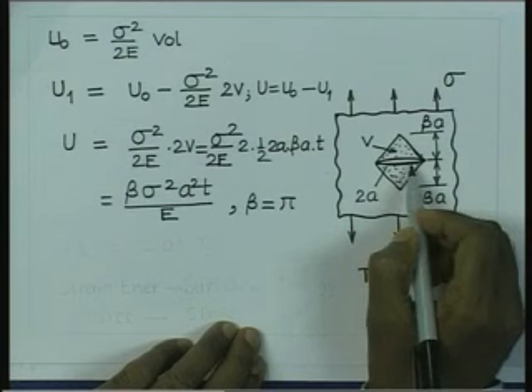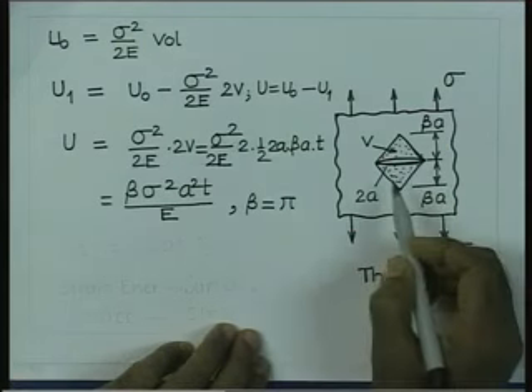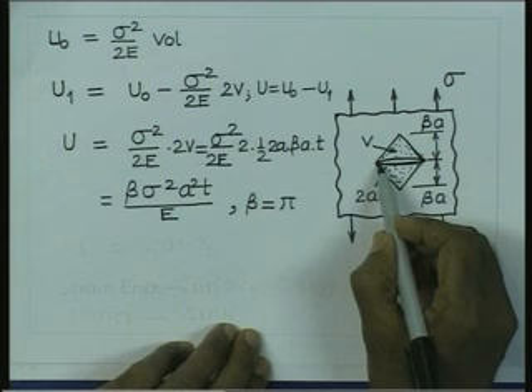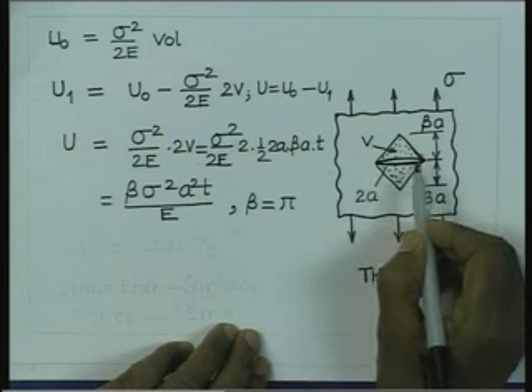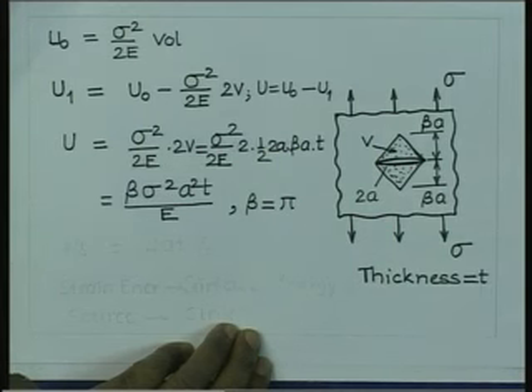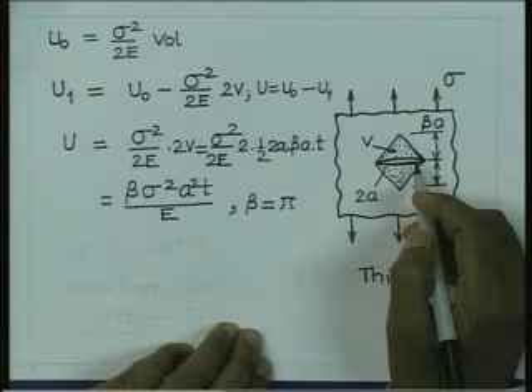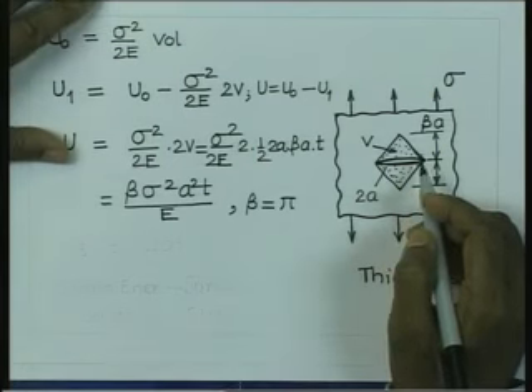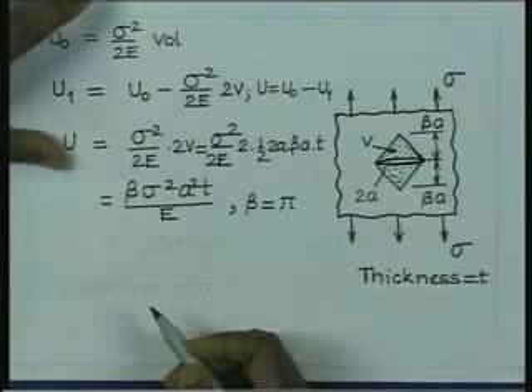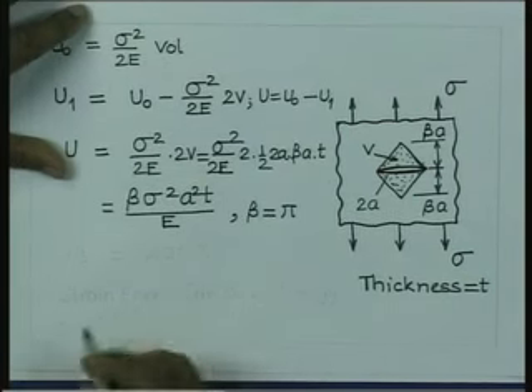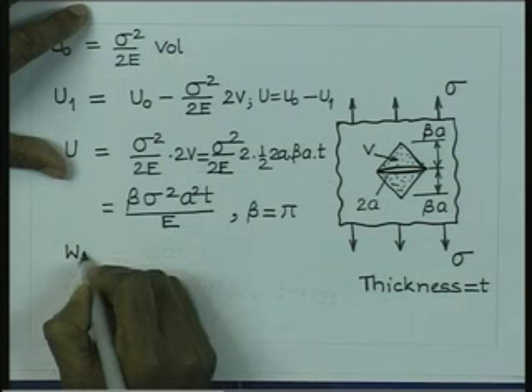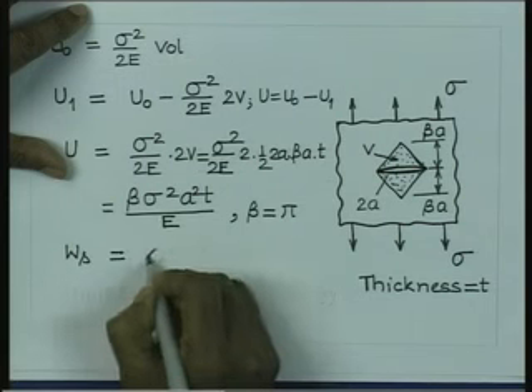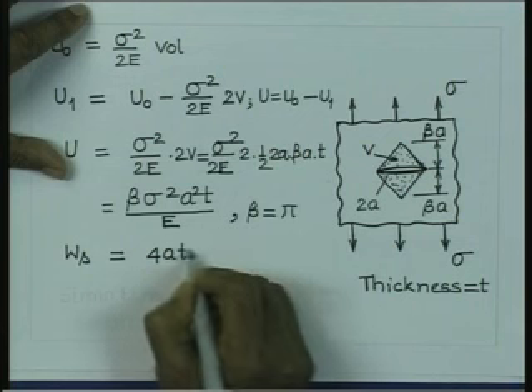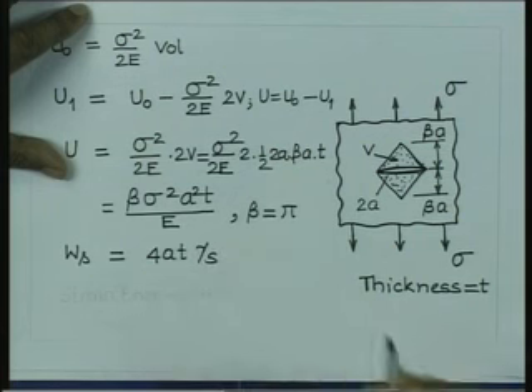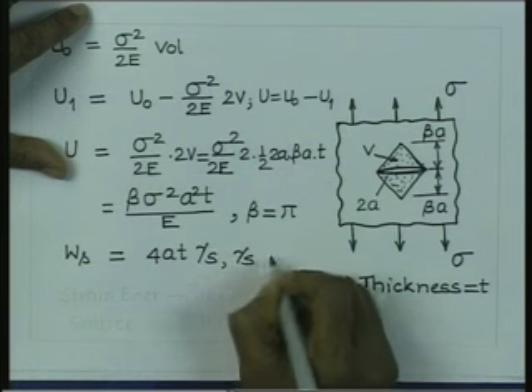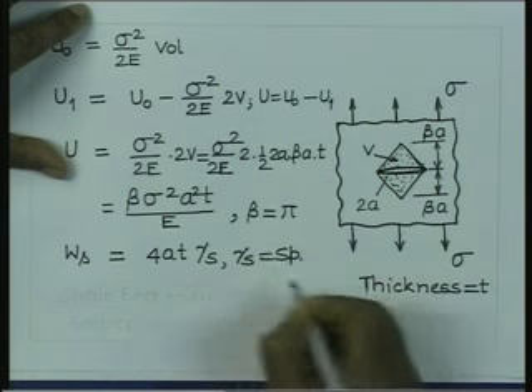of dimension 2a in the material, then we have created a surface of area 2at at the top, 2at at the bottom. So, therefore, total area is 4at, and therefore, the energy that has got converted into surface energy is given by 4at multiplied by the specific surface energy. So, we can write now that the surface energy of the cracked body is nothing but 4at multiplied by gamma s, where gamma s is the specific surface energy.